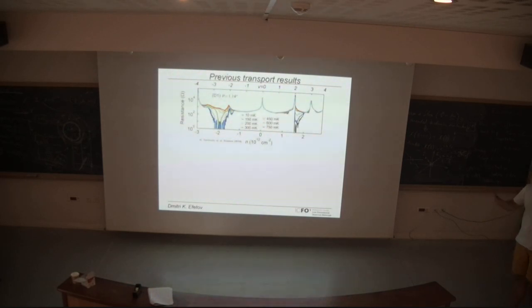So, this is experimental data, which I also discussed last time. Again, what we measure in transport is just resistance as a function of carrier density. We vary the filling in the bands just by applying an electric field to a backgate. These high resistance regions here are the band insulators. Then this is the Dirac point, and these peaks here were the peaks at fillings of 2 and -2. And as you can see, resistance drops next to it, and we observed superconductivity.